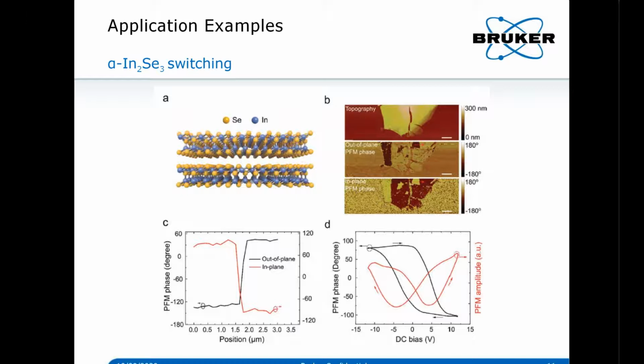This is published from the AFM using our ICON system. You can see from the topography we have this 2D material flake. This one is relatively thick. And if we do the PFM on this flake, we can see that it possesses both in-plane and out-of-plane responses, which some people call out-of-plane, in-plane. Sometimes you call it lateral, horizontal, lateral or vertical. It depends on how you define it.